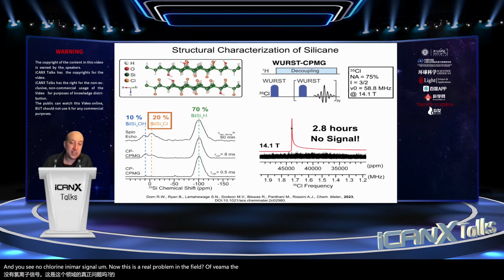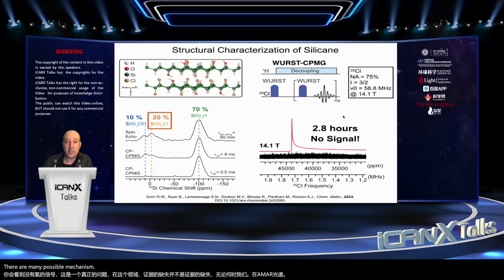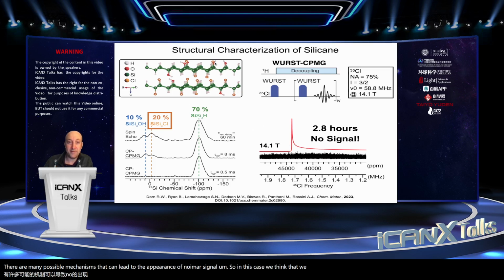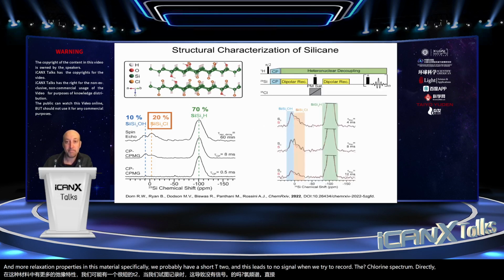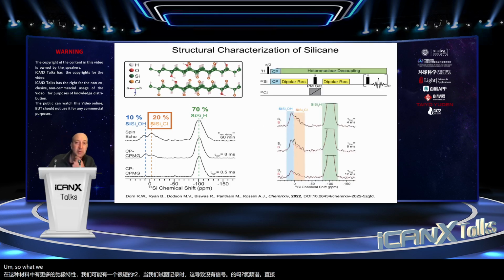Now, this is a real problem in the field of NMR. The absence of evidence is not the evidence for absence whenever we do NMR spectroscopy. There are many possible mechanisms that can lead to the appearance of no NMR signal. So in this case, we think that we just have unfavorable chlorine NMR relaxation properties in this material. Specifically, we probably have a short T2, and this leads to no signal when we try to record the chlorine spectrum directly. So what we did is we switched to an indirect detection strategy.